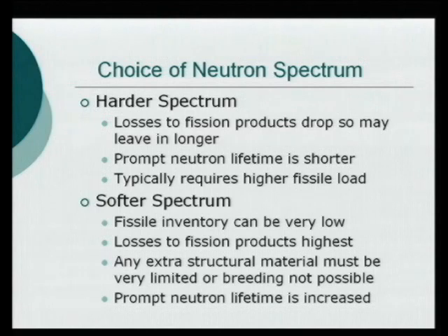Softer spectrum is basically the reverse. We can get that fissile inventory really low. The losses to the fission products, though, are going to be higher, so we might need to remove them quicker. We can't really have any extra structural material. Most designs don't have any at all. It's just graphite and the salts, and graphite is very good with neutron absorption. And the prompt neutron lifetime is much increased, so things can happen slower here.